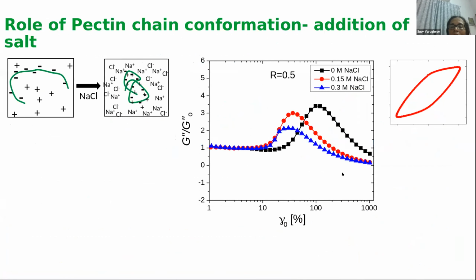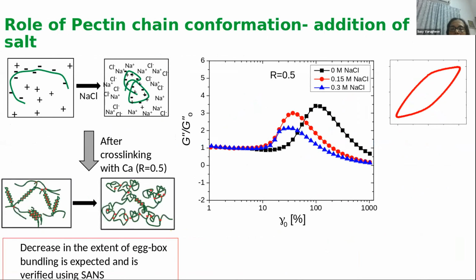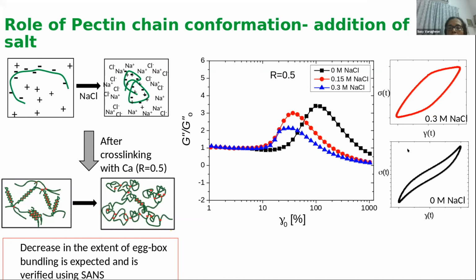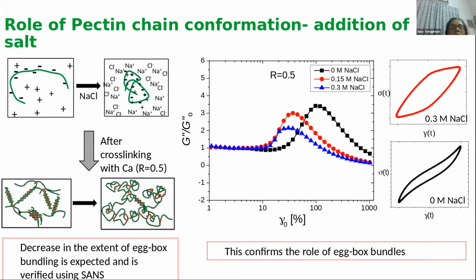To confirm this, and to check whether there is any contribution from pectin chain conformation, we added some salt while the gel was forming, and looked at the rheology. When there is no salt, the black curve shows that the dissipation is very high, and you have the strain stiffening behavior that you can see here. When you add some amount of salt, it moves to more of a strain softening-like behavior, which again has implications from the morphology. The salt is screening some of the charges on this material and not allowing the formation of these dimers.